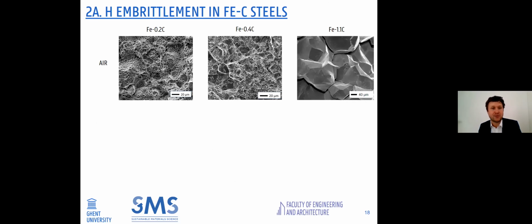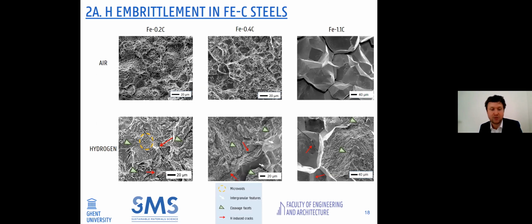If we then inspect the fracture surface, we can clearly see in the air tests that we move from microvoid coalescence in the 0.2 to an intergranular type of fracture for the 1.1. But when we charge with hydrogen, we have the additional presence of cleavage, indicated by the green arrows. So in the 0.2, we can see these cleavage facets, but also in the 1.1, we have a change from intergranular to cleavage when hydrogen is present, which is quite contradictory to what was stated before. So this is quite interesting to discuss.